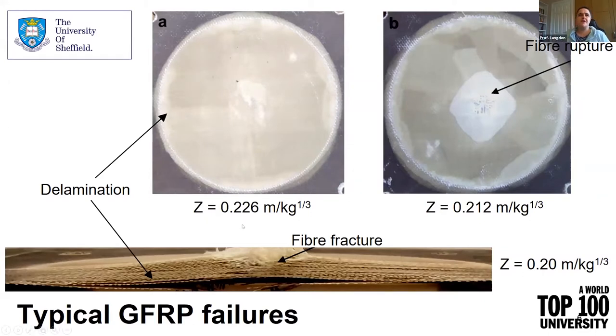So the Z value is a way that we look at scaling an explosion. Z would go lower as you increase a charge mass because it's a scaled distance. So the lower the Z value, the more extreme the loading in terms of explosions. And so the lower Z value on the right-hand side shows a more extreme failure where you've got a diamond of delamination that is extremely white, even whiter than the other delaminations on the left-hand side. And hopefully right in the center, you can see that there's some fiber rupture there. If you go down to the bottom image on your screen, which is where we take that panel on the right-hand side, cut it in half and have a look at the cross-section, you can see multiple delaminations, multiple fiber fractures happening.